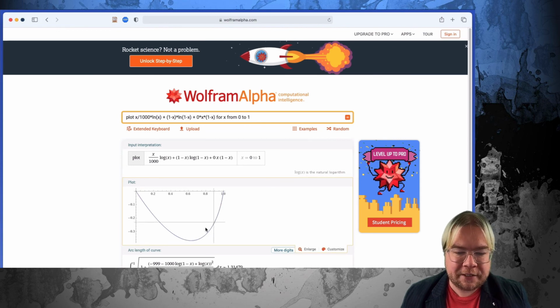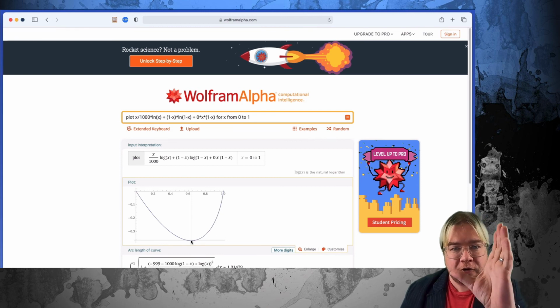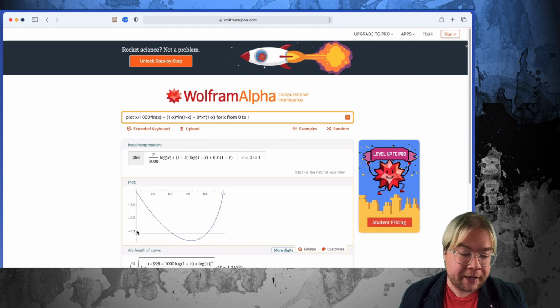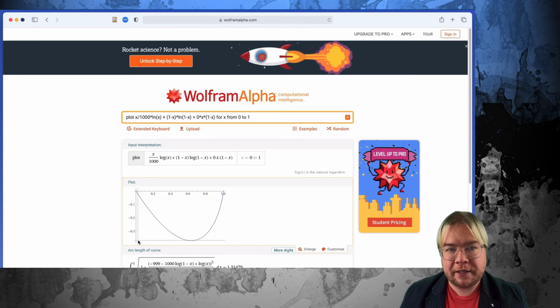But the overall shape is still the same, and in addition to the curve being skewed to higher volume fractions, instead of taking a value of minus 0.6869 at its minimum, now we're looking at minus 0.3 something. So the free energy difference between the mixed and the unmixed states has decreased relative to the regular solution because now we've got a big degree of polymerization for the polymer.